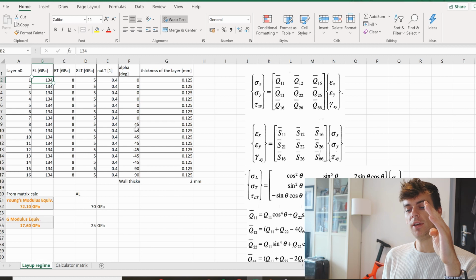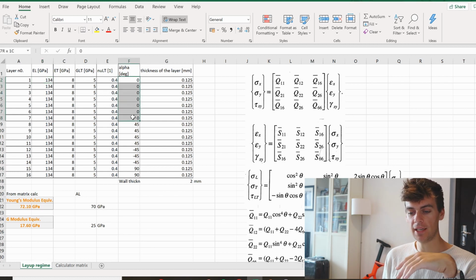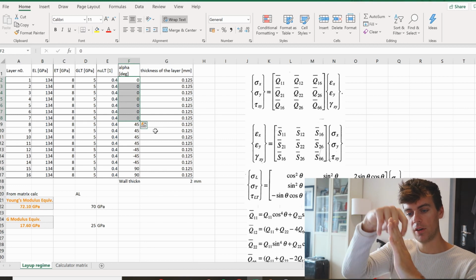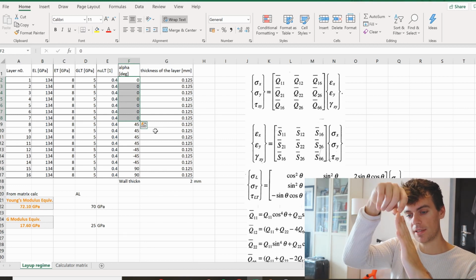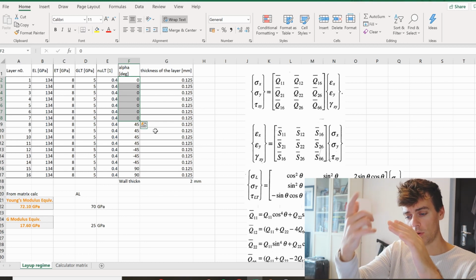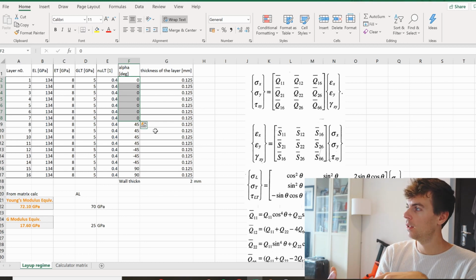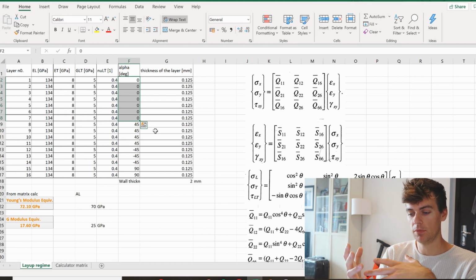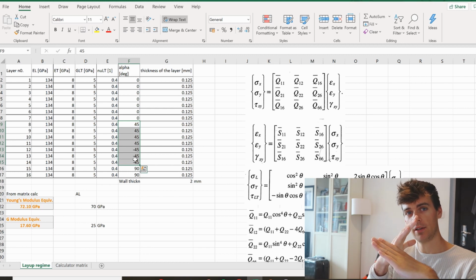So the first 7 layers here are laid up at 0 degrees to the loading. So that's very high tensile stiffness that way, which is used for the bending of the down tube. Like I said, the rider weight, some of the braking and the bump forces will use these layers for the stiffness. You then have a number of layers at 45 and minus 45, across the length of the down tube, and that gives you the torsional stiffness of the down tube.